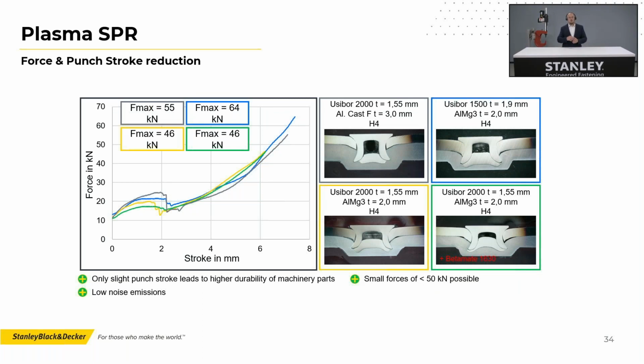You can see here four force curves, and the force curves look different than what you would expect when you just set these kind of ultra high strength steels and compare the curves with one another. First of all, the force is much lower. So the end force is much lower. Usually what happens is that the force of the setting peaks when the rivet head touches the top material and presses into the top material. This is where you get the 80 kilonewtons or above, right? But if the top material is still a little bit soft, you don't get that peak. So you are at the highest at this one. It's a little bit far away, but I think 64 kilonewton was the highest one that we got on these trials. And remember, that's a 2000 megapascal, 1.55 millimeter top sheet.